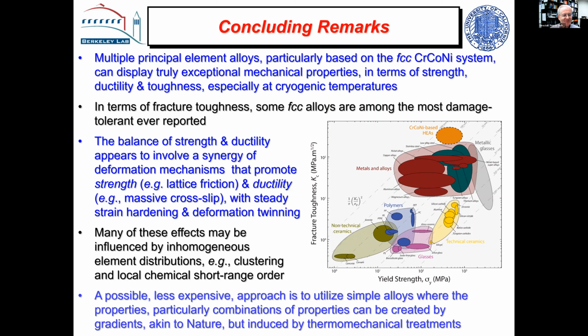So I think there probably is a region of J dominance, but it's so narrow you never see it. So the variability in the toughness of metallic glasses, I think, is a problem, because I don't think you could ever use them as a real structural material, because you wouldn't be able to specify one of the major properties. But I also think that of all the toughness measurements that have been made on metallic glasses that are published in the literature, probably 60 to 80% of them are wrong. So anyway, that's my opinion. Yeah, thank you very much.